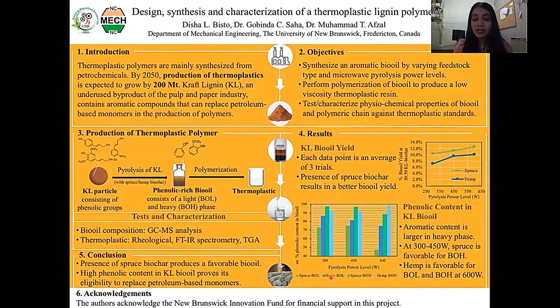At lower power levels, that is 300 to 450 watts, the phenolic content was larger in the heavy phase when spruce biochar was used, while the phenolic content in the light phase was larger when the hemp biochar was used. At 600 power level, it was observed that hemp was favorable for both phases in the bio oil. Based on our results, it was concluded that the spruce biochar was a favorable microwave receptor to be used as it can combine a good yield as well as good phenolic content in the bio oil.